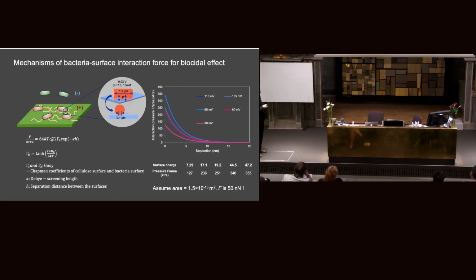The force was calculated, and we found that from lower charge to higher charge, the pressure can range from 127 to 355 kilopascals. If we assume the contact area is around 0.1 micrometer, we can get a contact area of around 1.5 times 10 to the minus 13 square meters, and the force can be calculated at around 50 nanonewtons. But if this area sometimes reasonably surpasses this estimate, for example if the bacteria are more elastic, then with more contact area, the force is even higher.